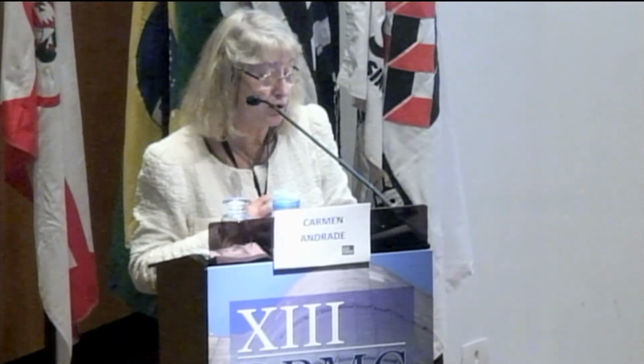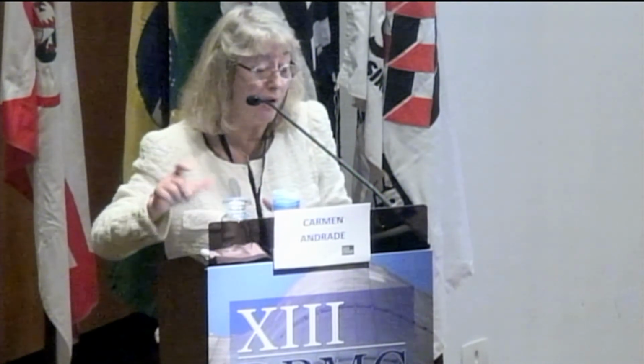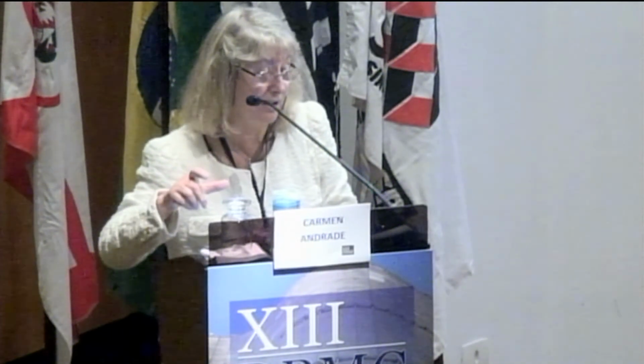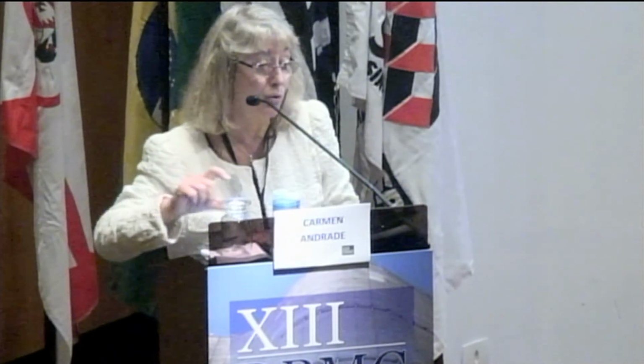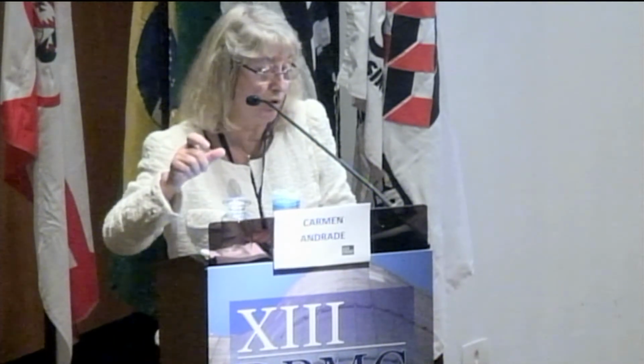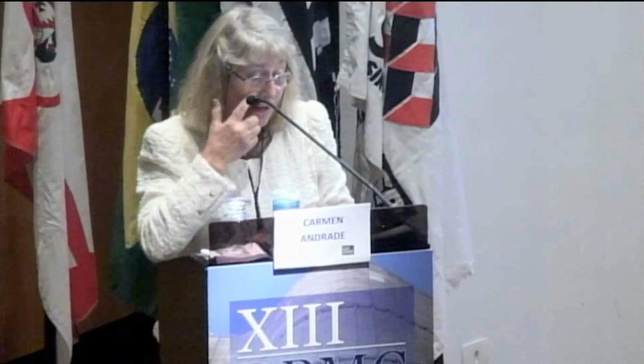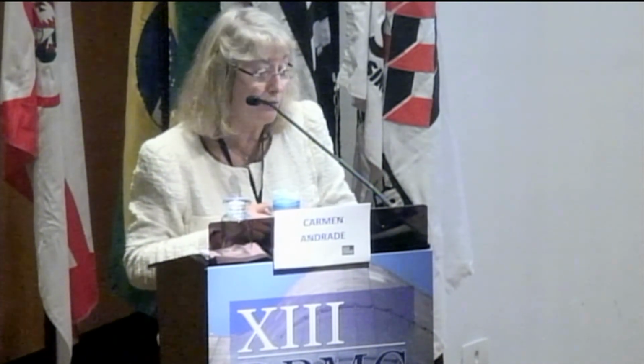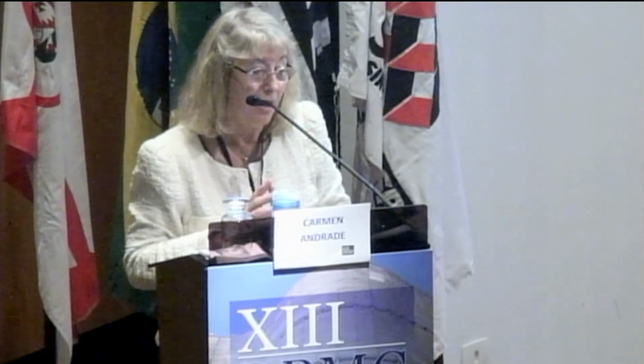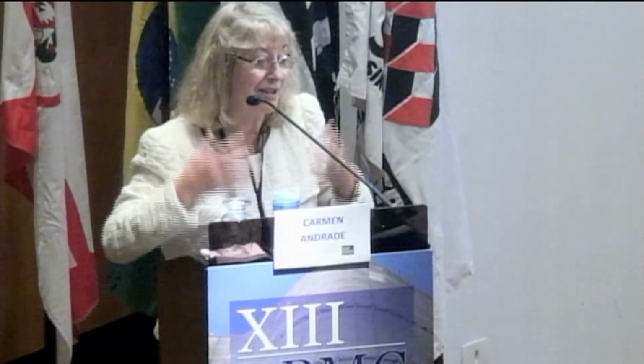We are in favor of the natural diffusion test in the European standard, and the only issue is that they have decided it is 1 year. It's too long for me. In my opinion, we should have a number at 3 months. If you don't have carbonation, it's because it's a good concrete, and you wait until 1 year to have some millimeters or more for having a velocity, a number. But natural diffusion is the most convenient. I know it appears too long, but this is too long to discuss here.